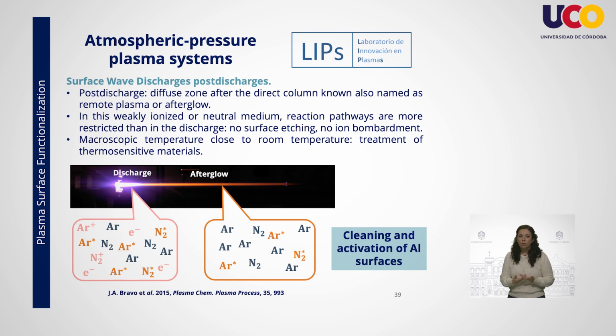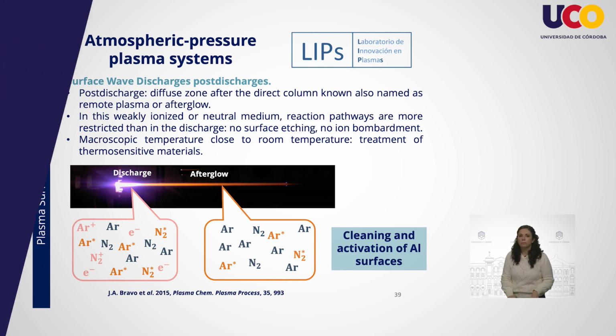Another interesting feature of these afterglows is that the macroscopic temperature of the gas dramatically decreases along the post-discharge, even reaching room temperature. All these features make the use of microwave afterglows very interesting for the treatment of thermosensitive material surfaces such as biological ones, without ion bombardment or etching of the surface. In this lecture, we will discuss the effect of argon-nitrogen post-discharges on the cleaning and activation of aluminum surfaces.